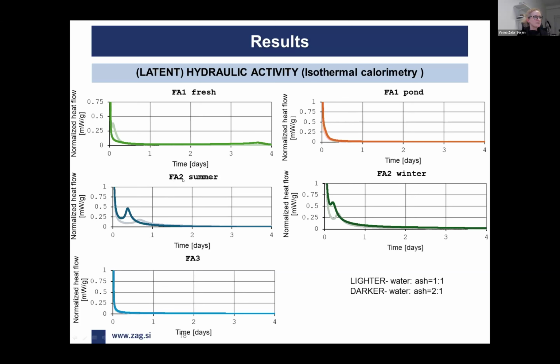For Fa2, in both cases, summer and winter regime, we can see the heat release, again, at relatively early ages of hydration. But in the case of Fa2 winter, the quantity of released heat is higher in both cases, when 1:1 and also when 2:1 water to ash was used. If we go further, Fa3 ash, similar to Fa1 pond, doesn't show any heat release. So what could be the reason for this?